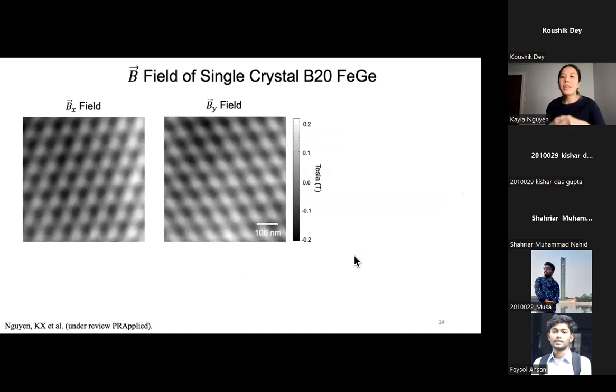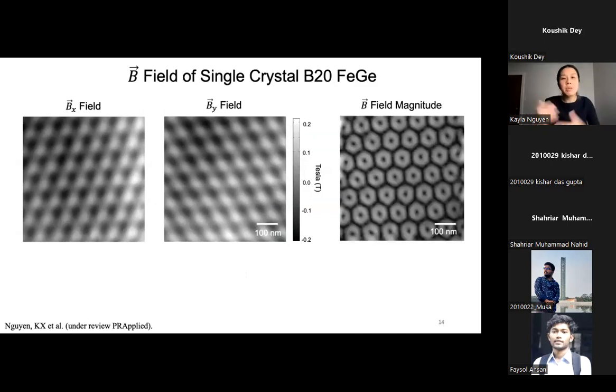Okay, great. So let's just put our sample into the electron microscope and perform our 4D STEM technique. What should we get? If we took a sample, for example, a single crystal of B20 iron germanium, they form skyrmions intrinsically. We look at the deflection in X and Y because we have a diffraction pattern. We can look at that change in momentum, and then we can take the magnitude of the signal and get back information related to the skyrmions.